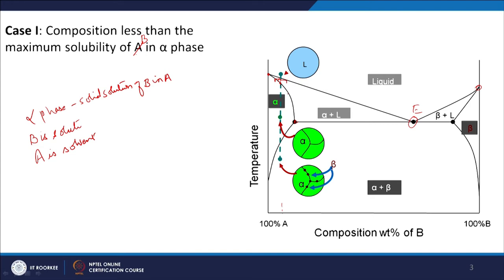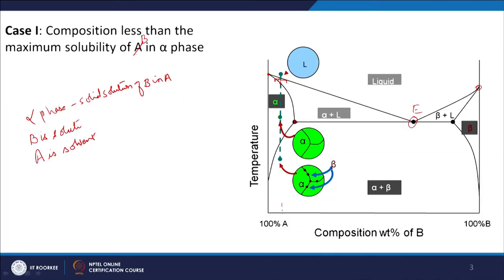It is shown here that the whole volume is now solid with alpha grains, and of course there is a boundary between these grains. Up to this point it is very similar to what we saw in the isomorphous phase diagram — the whole liquid transforms to a solid of one phase. Now, once we keep on cooling and the cooling crosses the solvus line — the solvus line between the alpha phase and the alpha plus beta phase region — as soon as it crosses the solvus line, some B atoms must come out because the solubility of B is decreasing.